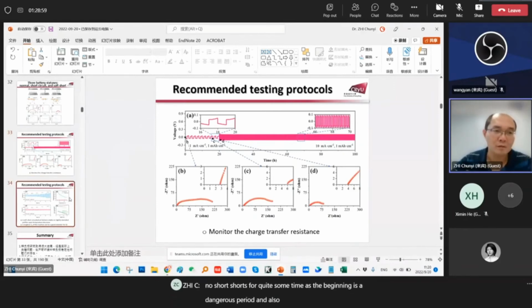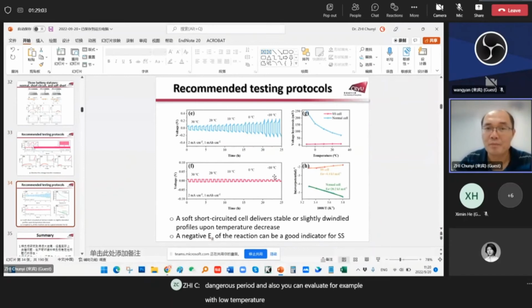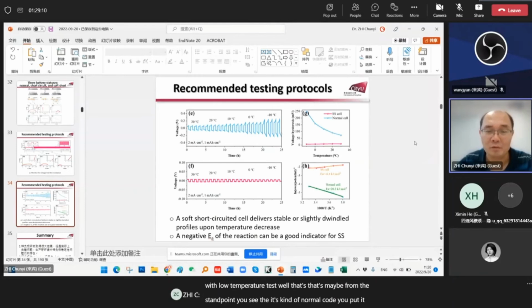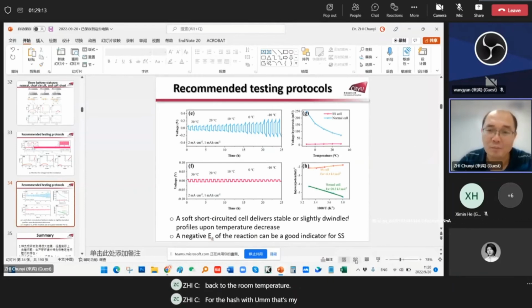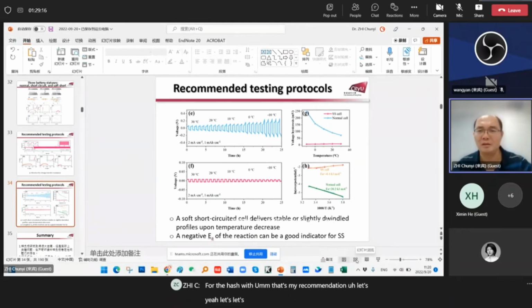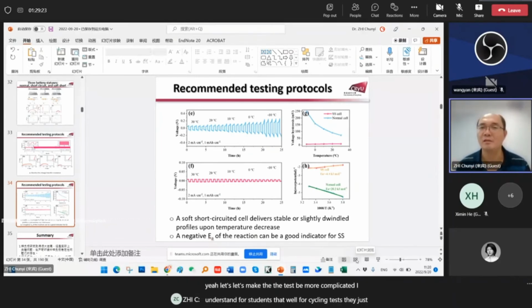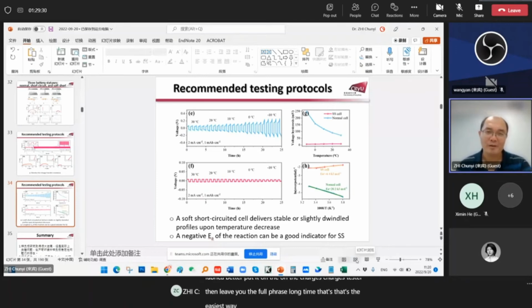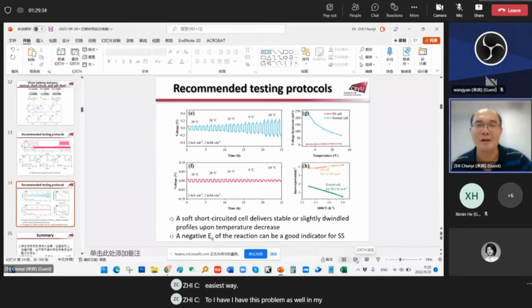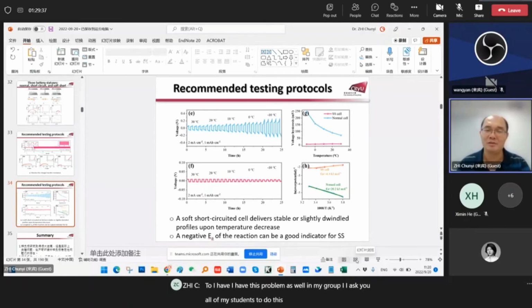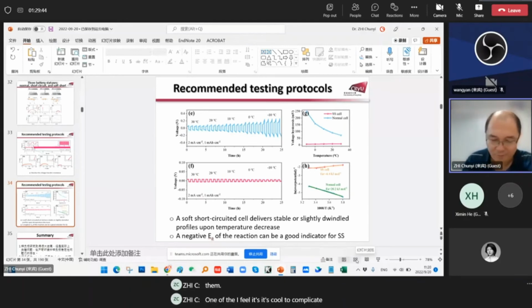You can also evaluate, for example, with a low temperature test. If from the starting point you see a normal curve, you put it back to room temperature for testing. That's my recommendation. Let's make the test more complicated. I understand that for students, for a cycling test, you just fabricate a battery, put it on the charge tester, and leave it for a long time. That's the easiest way. I have this problem in my group as well. I ask all of my students to do this kind of precise test, but some of them find it too complicated. Well, that's my observation. Thank you.